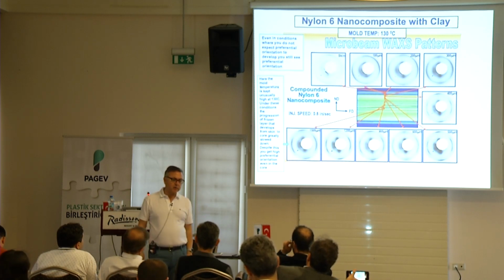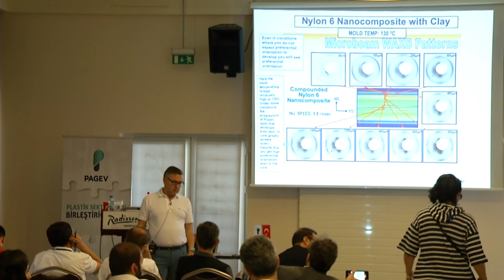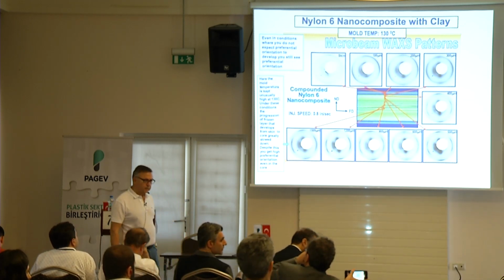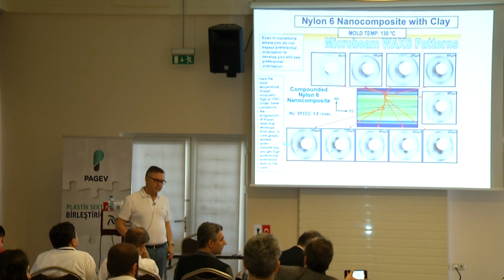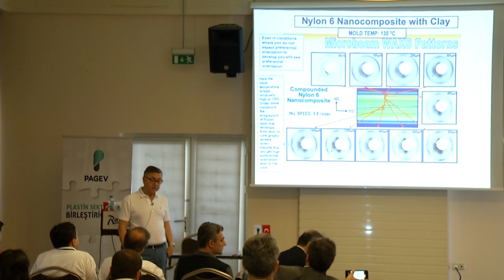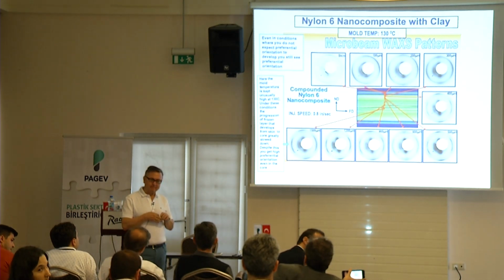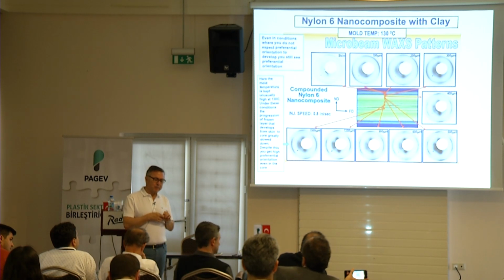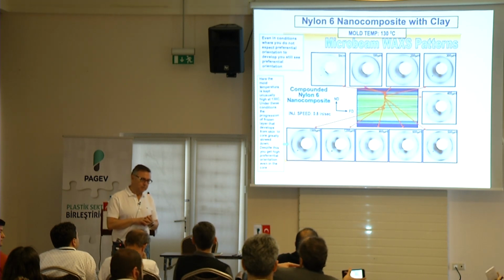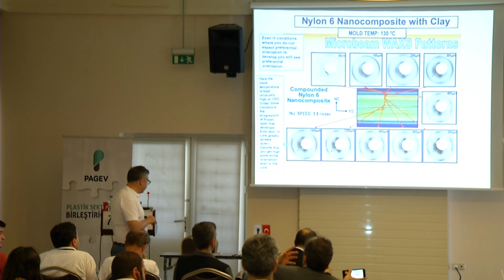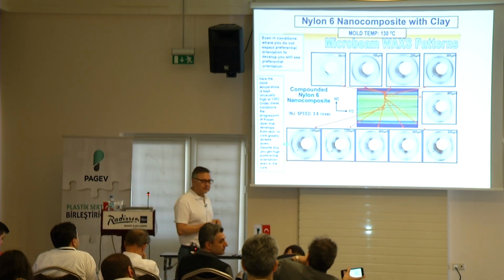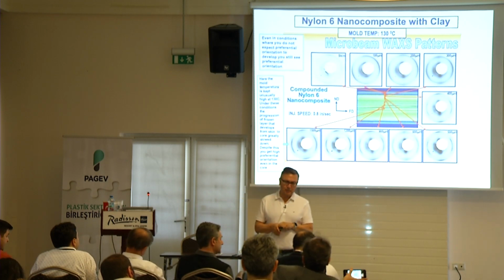What film thickness did you end up with? 100 microns. But we put them in the core layer, which was 45 to 50. It was a coextrusion process, and the core layer was 50 microns. Even then you get defects? Yeah. But the mechanical properties did not alter. The elongation at rupture didn't change. But water vapor transmission went up. Yeah, but I must play with process parameters. For instance, the inner layer temperature and the external temperature can be dropped, maybe that can influence it.